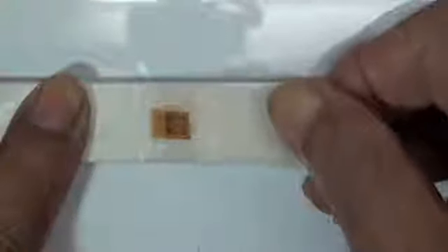So he's going to lift this gauge again at a shallow angle, just a little bit, a few millimeters past the end of the tabs, or the end of the strain gauge, to allow room for the adhesive to flow. About 5 or 6 millimeters past the edge of the tape.